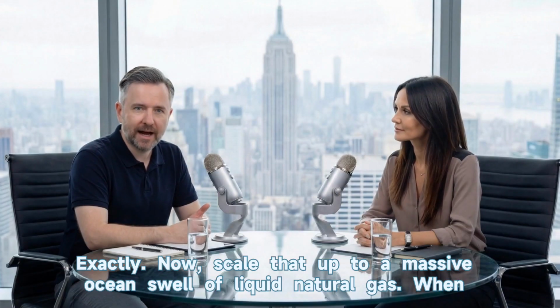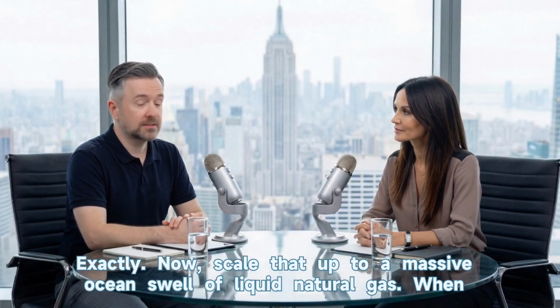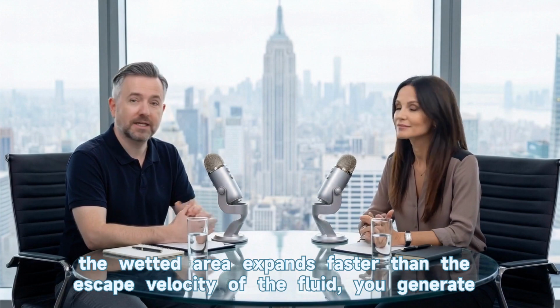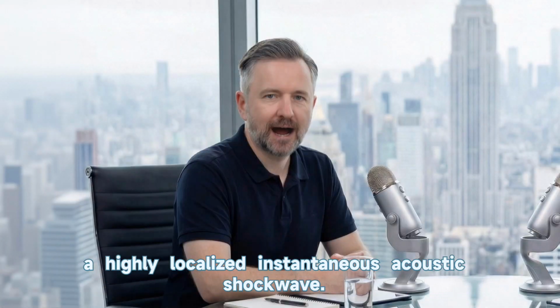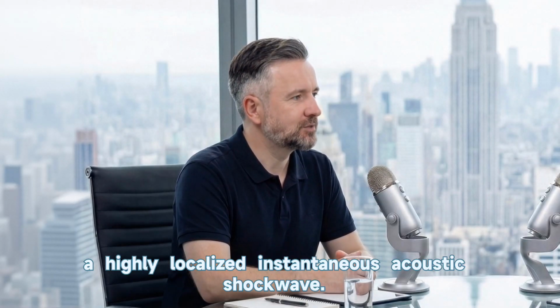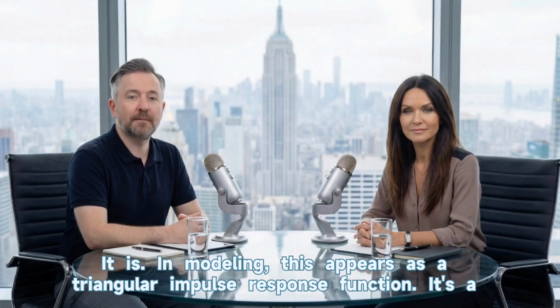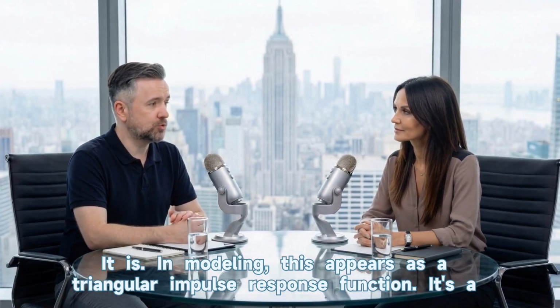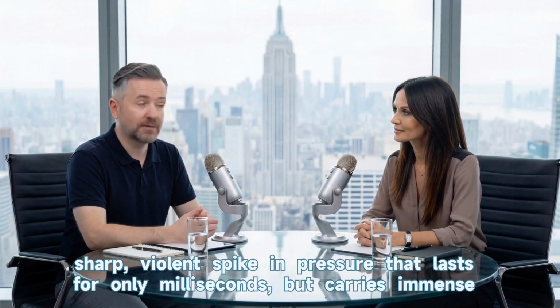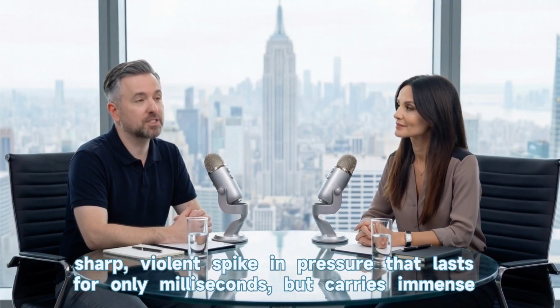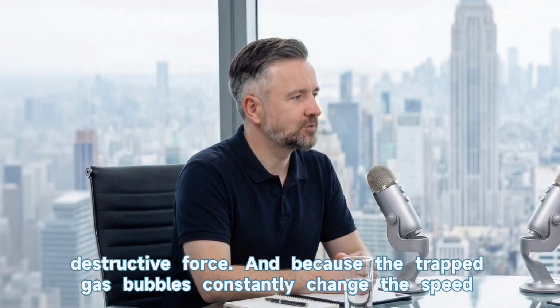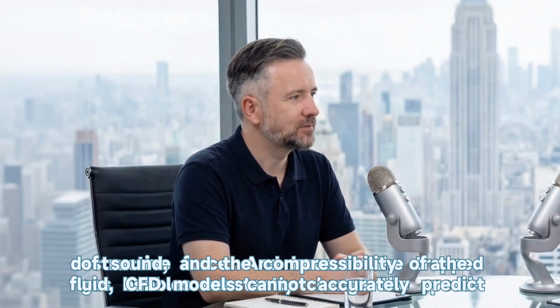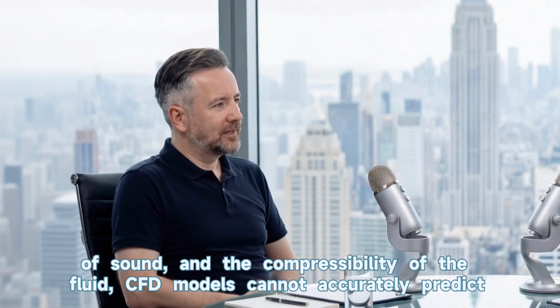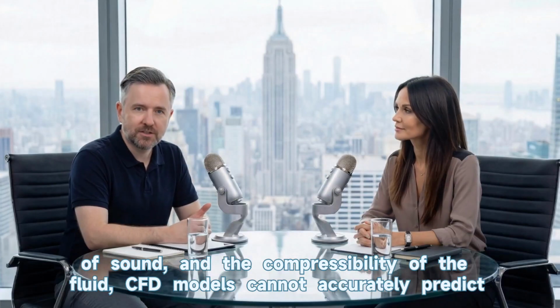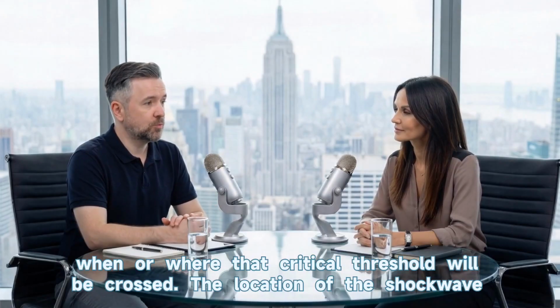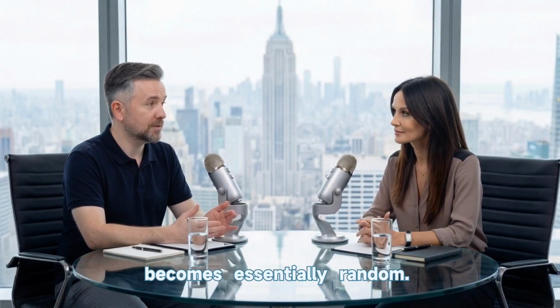Exactly. Now scale that up to a massive ocean swell of liquid natural gas. When the wetted area expands faster than the escape velocity of the fluid, you generate a highly localized, instantaneous acoustic shock wave. That sounds destructive. It is. In modeling, this appears as a triangular impulse response function. It's a sharp, violent spike in pressure that lasts for only milliseconds, but carries immense destructive force. And because the trapped gas bubbles constantly change the speed of sound and the compressibility of the fluid, CFD models cannot accurately predict when or where that critical threshold will be crossed. The location of the shock wave becomes essentially random.